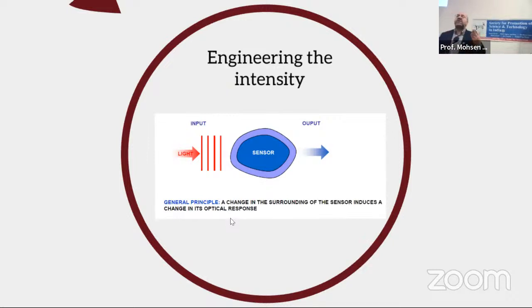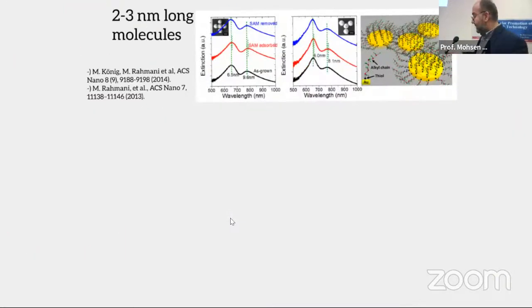These nanostructures are well known to be very sensitive to the refractive index of the environment. So if you introduce some new substances to them, the refractive index changes, and that change can change the optical properties. By detecting these optical properties before and after introducing the new substance, you can determine the existence or absence of some particular elements. For example, this is again a paper from the time I was a postdoc at Imperial College. We showed that this kind of nanostructure can be used to detect alkyl molecules, which are around 2-3 nanometer long, but optically, with these nanostructures, we can detect their presence.